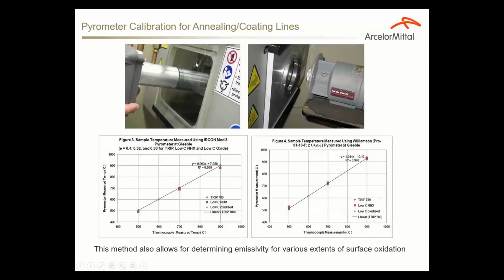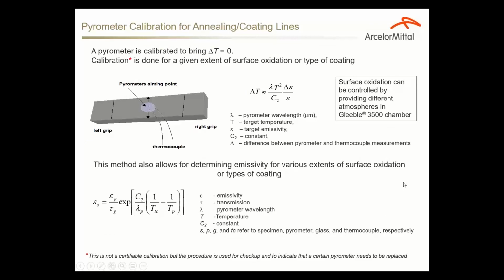Specifically, in the chamber, we can achieve different kinds of atmospheres and different extents of surface oxidation. We can closely simulate how the strip oxidizes in the annealing and coating line, how its emissivity changes during heating and cooling, and what the pyrometers see in the mill, how they measure temperature, and how it compares to the actual temperature of the strip. This is data fed directly into the annealing and coating line control system.